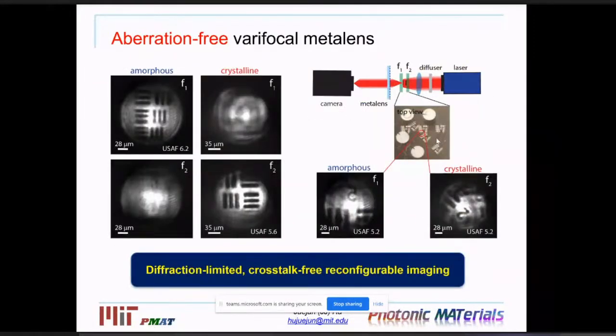Now, just as one way to imagine how we can apply this technology, we demonstrated that we can use such a varifocal metalens to realize multi-depth imaging. What we did is we placed two optical targets containing different patterns at two different depths that coincide with the focal planes of the lens. If we switch this lens between these two focal states, we are seeing only one object at a time, with very little crosstalk from the other state here.